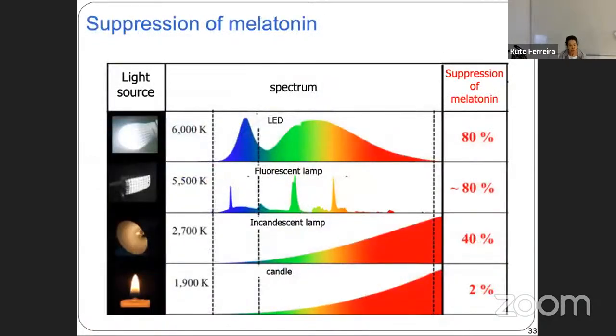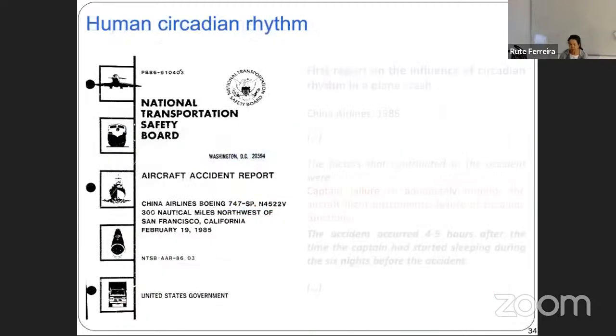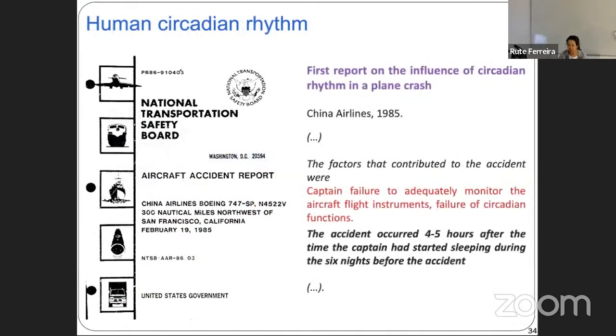And here I show you how CCT is strictly related to the suppression of melatonin. High CCT values may lead to a suppression of melatonin of the order of 80%, whereas, for instance, under candlelight illumination, the suppression will be only 2%. And the relevance of the control of the circadian rhythm is well illustrated in this example.